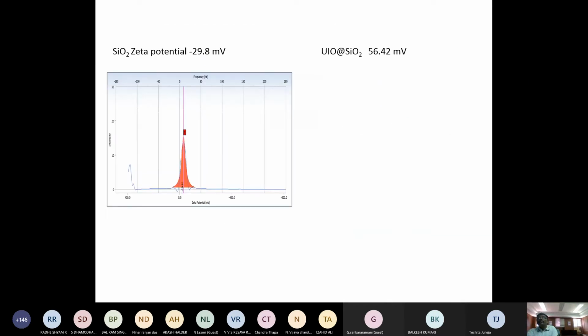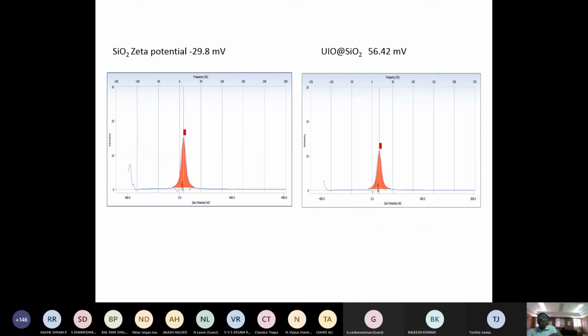Then when we measured the zeta potential, we got nearly 56 millivolt, so 56.42 millivolt. That means the surface is capable of capturing all the negatively charged polysulfides due to the electrostatic attraction between the two systems.